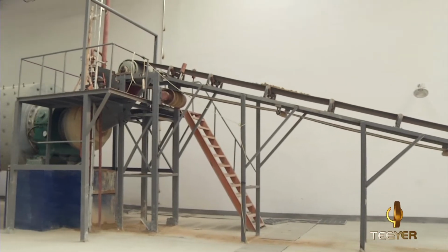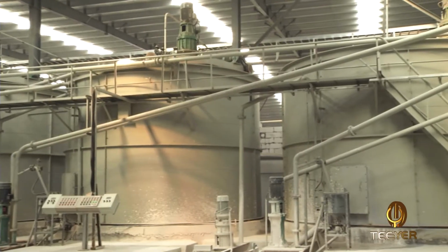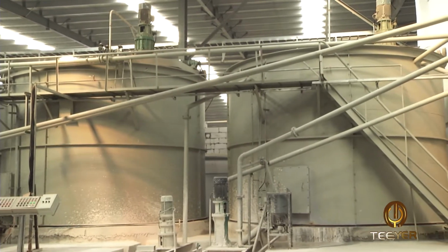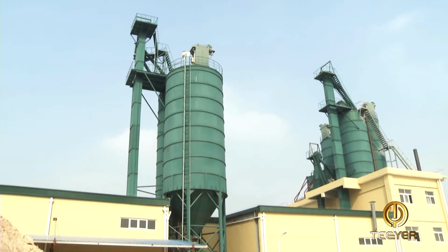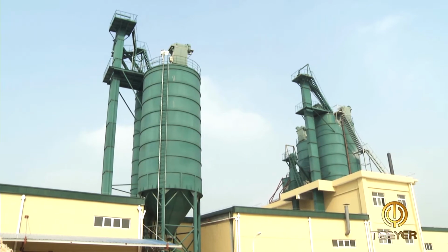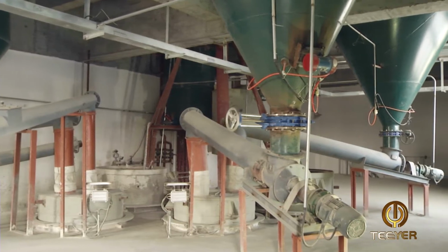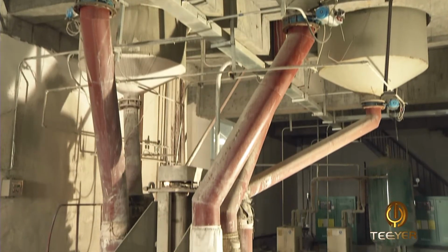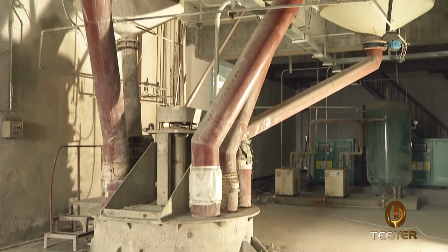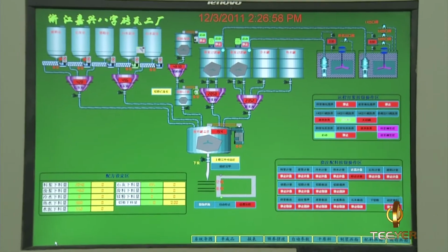Operation principle of autoclaved aerated concrete production. At first, pulverized fly ash or sand are ground through the ball mill and made into slurry stored in a storage tank. The cement and the lime which has been processed are respectively conveyed to the cement silo and lime silo. The raw material which is prepared is metered with an electronic scale and then conveyed to the mixer for high-speed mixing. All scaling processes above are automatically controlled by PLC.